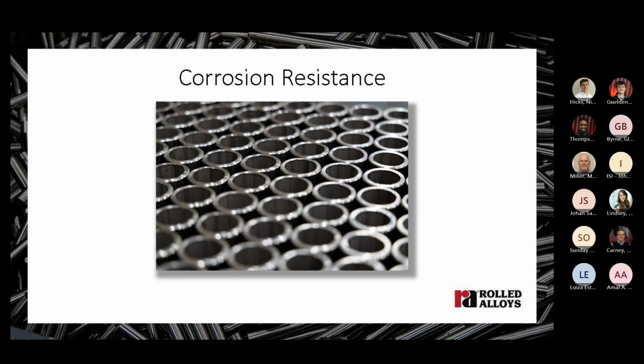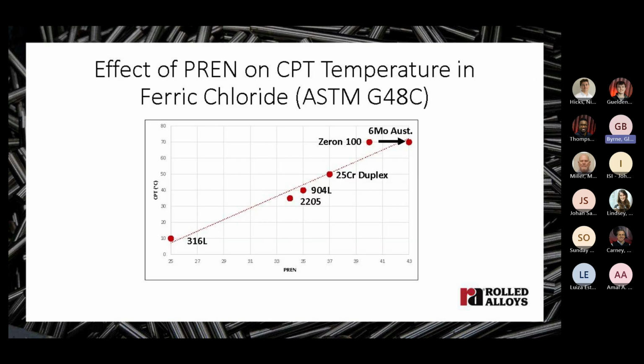Okay, let's talk about corrosion resistance a little. When we plot the pitting resistance equivalent number versus the critical pitting temperature, we find that as the PREN increases, the critical pitting temperature increases too. This is in a linear fashion, you see in this graph. This is also true if we measured the critical crevice temperature. This trend holds for most oxidizing chloride solutions.